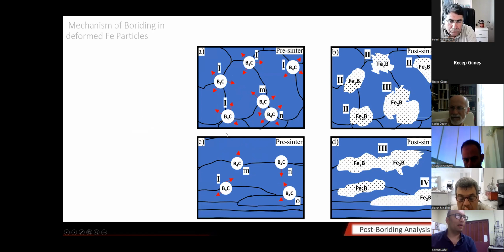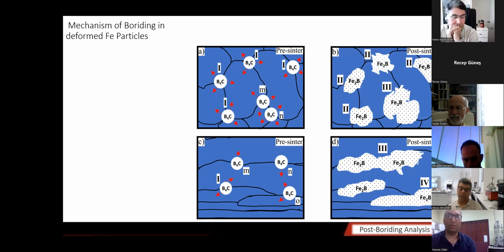Here I have explained the mechanism of boriding. I and II, this is the pre-sinter state on the left side, and this is the post-sinter state on the right side. These images are taken from the cross-section, and these images are taken from the longitudinal view. These are schematic images I have made, not taken images, but a schematic representation. I and II particles combine together to form Fe2B phases. No matter if it belongs to a different B4C particle, eventually these phases will merge, because these phases will merge together using a higher reinforcement ratio of B4C particles. You can have a higher borided region.